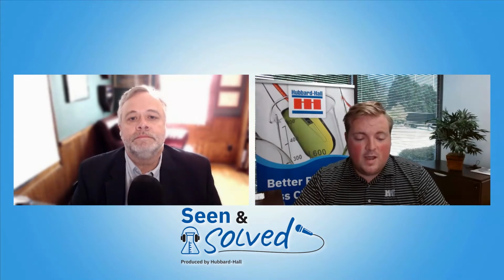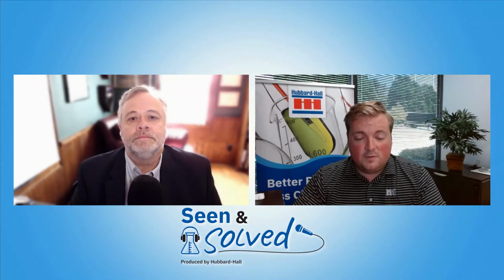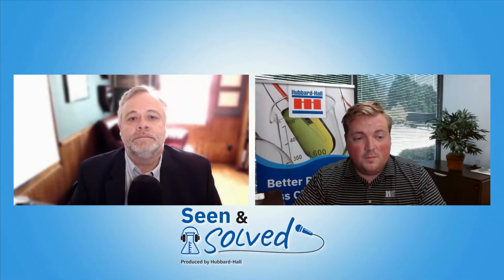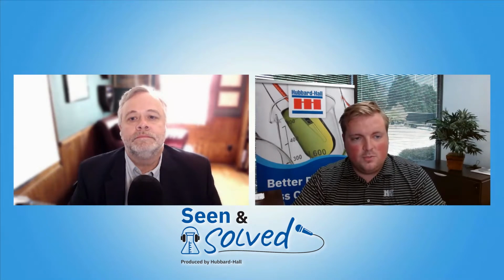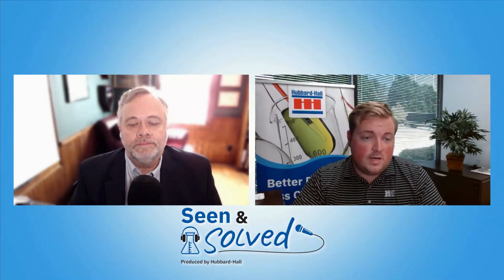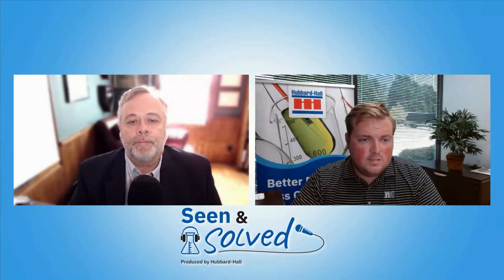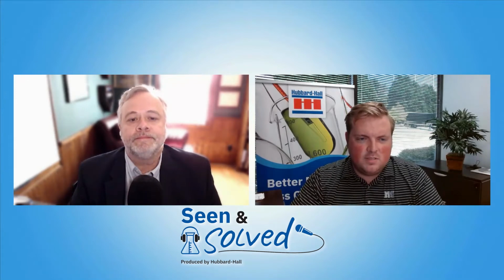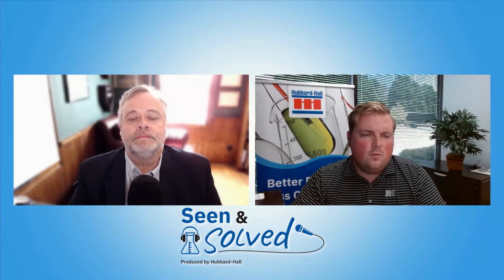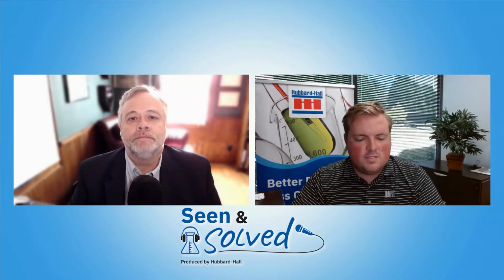Both of these reactions are actually very complex in their own right. Manganese, for example, has close to 20 different competing reactions that all have to take place in equilibrium in order for it to produce the desired coating or the desired crystal that you're trying to achieve. Zinc's a little less complicated, but still has that delicate balance of an equilibrium in the chemistry. In order for it to be a sustained reaction, it's going to produce a uniform and efficient coating.